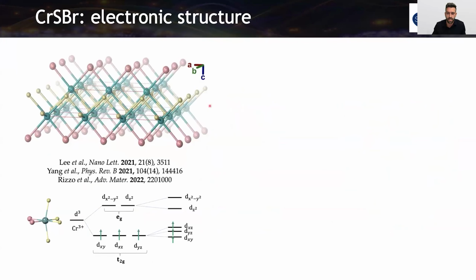So to start, I will start with the chemical structure. The material crystallizes in an orthorhombic structure. And as we can see here, these chromium atoms that are the magnetic atoms, they have different bonds depending on the direction of the space. So along the A direction of the crystal, we have sulfur and bromide. They are forming almost 90 degrees bonds here. Whereas if we go along the B direction, that is the easy axis of magnetization, we have these sulfur bridges of around 160 degrees. So this is an anisotropy in the structure.